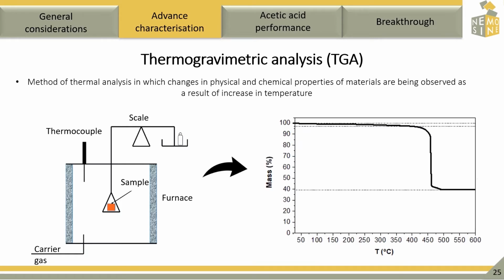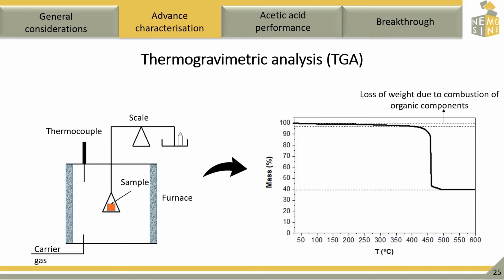Here, we can see a typical graph obtained by this method. The weight percent curve is primarily used to determine the amount of weight change of each decomposition step in the MOF material. Normally, the first step, at low temperatures, is related to the decomposition of organic compounds. After, the mass loss is due to residual solvent, and at higher temperatures is when we can see a metal oxide as a residue.